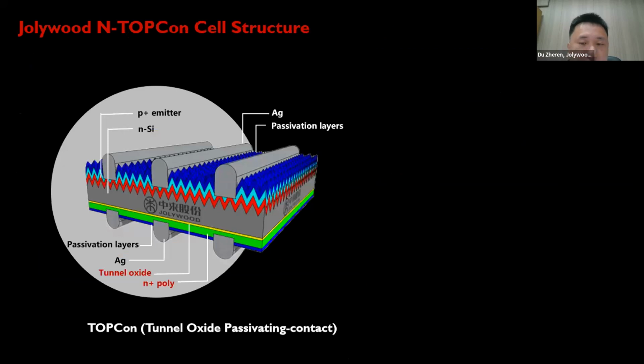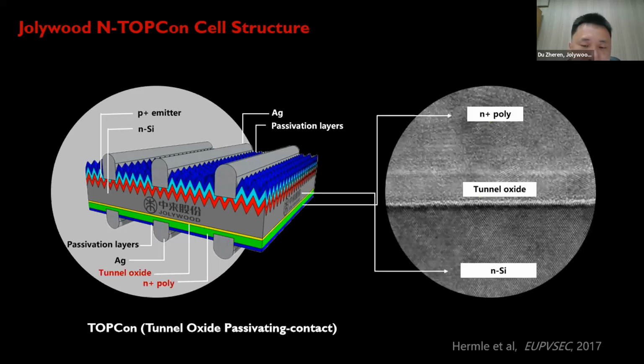Here's the structure and the properties of a TOPCon cell. TOPCon is the short form for tunnel oxide passivating contact, and it has a tunnel oxide layer and a doped polysilicon layer. And this structure is very important to passivate the surface and achieve a very low contact resistance at the same time. And there are a lot of defects on the silicon substrate surface, and silicon oxide provides excellent chemical passivation. And the heavy doping in the polysilicon repels minority carriers, and hence it provides excellent field effect passivation.